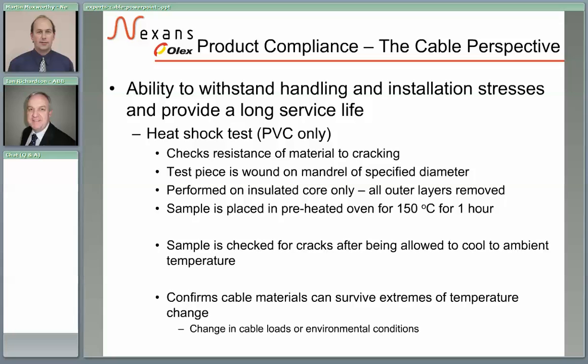Other tests that are done on PVCs, and again this is related to loss of plasticizer, is what we call a heat shock. Basically the test procedure involves winding the test piece, which is a sample of insulated core or cable, whichever the case may be, onto a mandrel of specified diameter, and this is aligned with the diameter of the test piece. When it's performed on the insulation material, all other layers are removed, and the test piece is placed in a preheated oven at 150 degrees for an hour, after which it's taken out and allowed to cool to ambient and is examined for cracks. So it's to simulate things like thermal cycling and rapid change in temperature, and a pass is achieved if there are no cracks within the material.